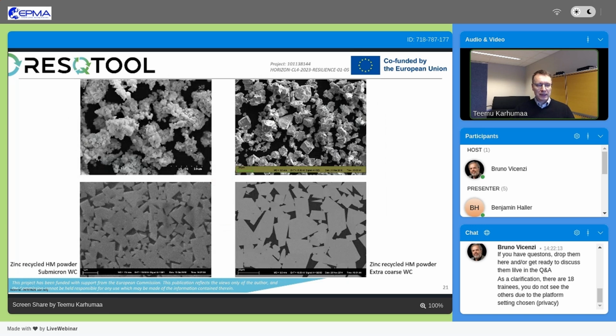And in terms of powder after the recycling, it can look something like this. In the picture above is the powder after zinc recycling. So there are agglomerates, loose agglomerates, which contain tungsten carbide and cobalt. So the zinc recycling does not purify anything. All the impurities that are in the scrap will be in the powder afterwards, as well as the tungsten carbide grains, so it does not change.